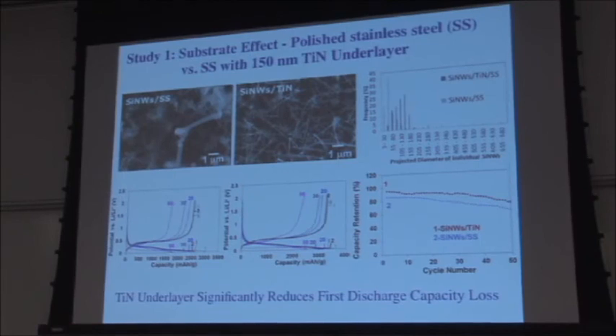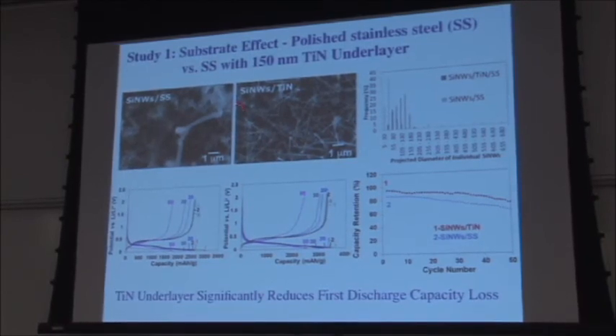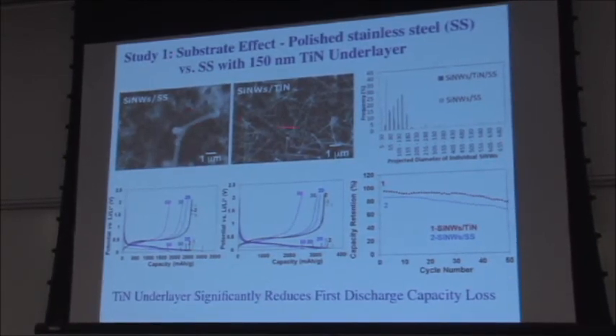circular discs. And what we found is that it actually makes a profound difference. The average diameter is about 100 nanometers in both cases. But here, you have these really coarse wires, these are really not even nanowires. These are fully microwires. You have some amorphous silicon. And equally important, you have very, very fine silicon nanowires. So if you look at the distribution, you have a lot of very small nanowires, and you have a lot of very large ones.